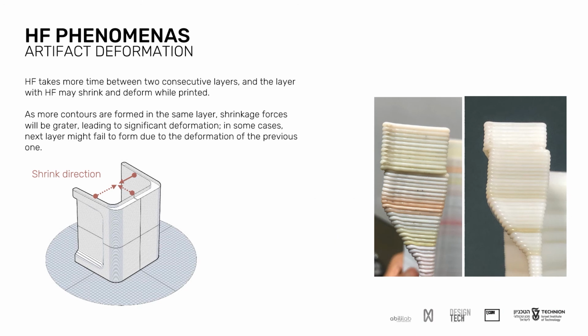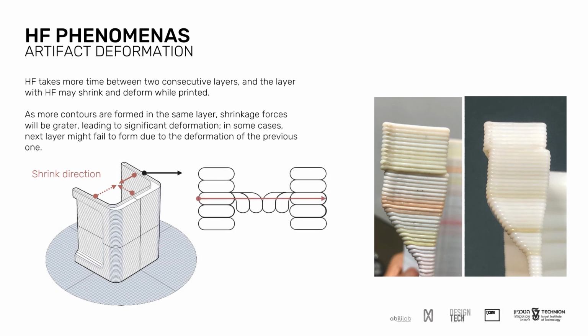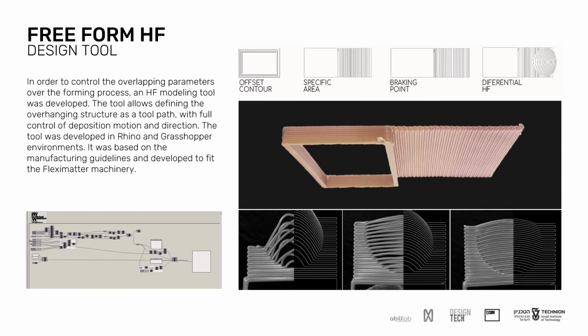HF takes more time to form a single layer. Moreover, having additional material at the same layer increases the shrink force and can lead to major deformation of the artifact while using material with a high shrink ratio. In the present method, HF can be generated as an offset of the original artifact. Based on the study, we developed a simple tool that allows defining the overhang direction and defining an area with the different classifications.